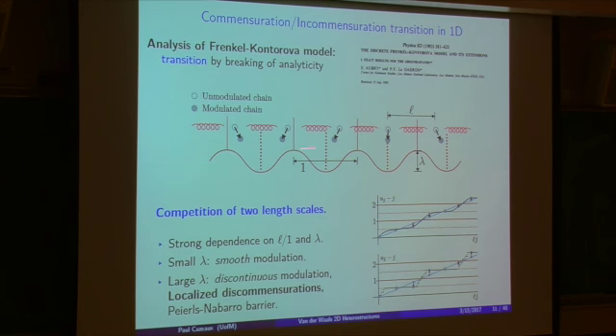However, if I increase this potential, at some point the atoms will basically all be sitting in the wells, and there will be some forbidden positions. The atom cannot sit on top of the wells. Therefore, as I pull, I need to impart some finite amount of energy, the so-called Peierls-Nabarro barrier, in order to pull the chain. In practice, this looks like having some local discommensurations, where we have the atoms sitting periodically at the bottom of the wells, and then somewhere there is an atom missing or something like this, and this is very localized.